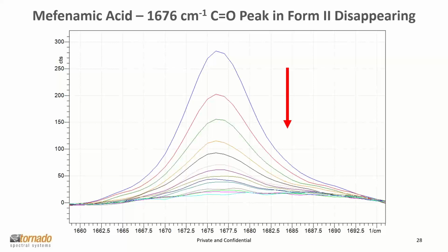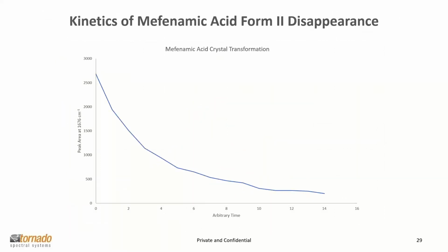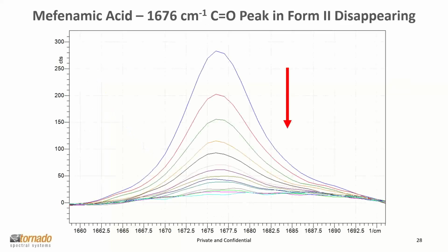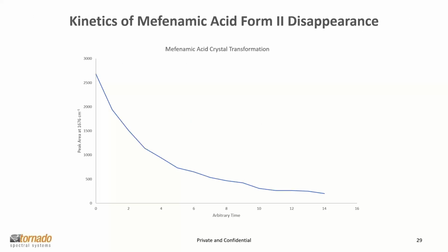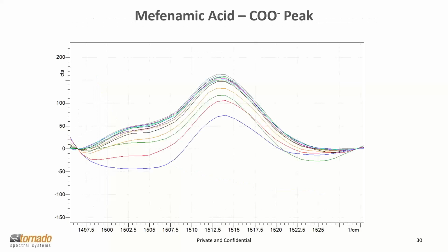And so we can simply latch on to this band very easily in the carbonyl region, which is often a diagnostic area for Raman spectra when we're looking at dynamic processes such as crystallization or reaction monitoring. And in this case, we could follow that very nicely, and we can see a trend. So depending on the level of interest that you have in terms of what you're using the PAT tool for, if it's just simple trend monitoring, we can look at that peak disappear over time, and we can look at the trend in that peak disappearance to get some kinetics information.